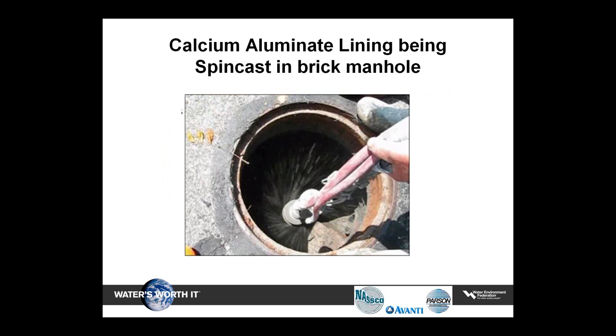Calcium aluminate cement with select aggregate products usually have a reduced working time versus Portland cement due to the increased internal heat that is naturally generated by the calcium aluminate cement. And as the ambient temperatures increase, that working time may be reduced even further.